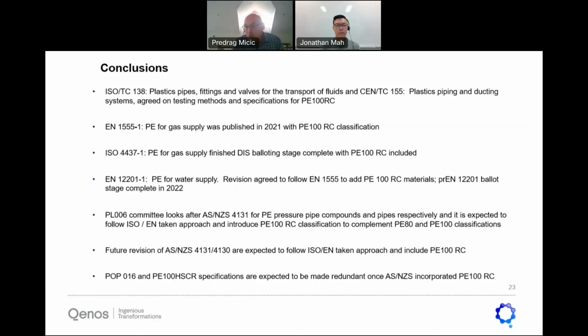And they could be relevant to open cut method, when you do not have slow crack growth imperfections. You have a sand laying, you cut the sides of the notch, so there is nothing poking in the pipe, etc. So maybe somebody can extract some value there, with very careful installation, but there is no really clear relevance of the ductile performance and higher MRS to the benefits in trenchless installation.